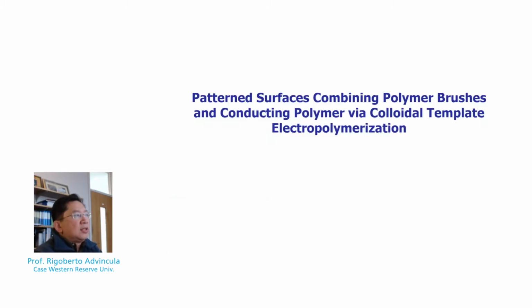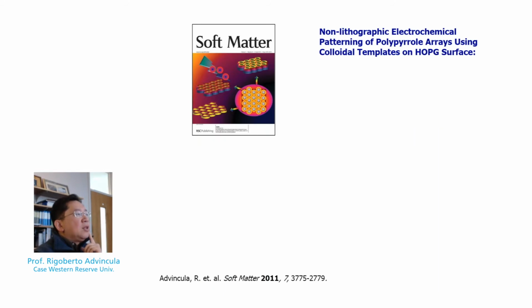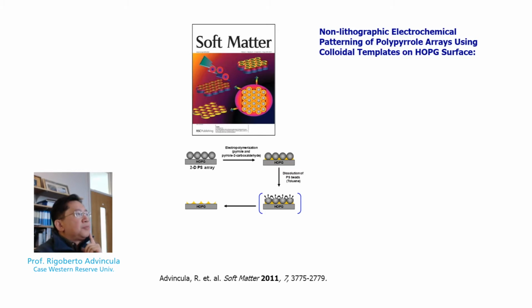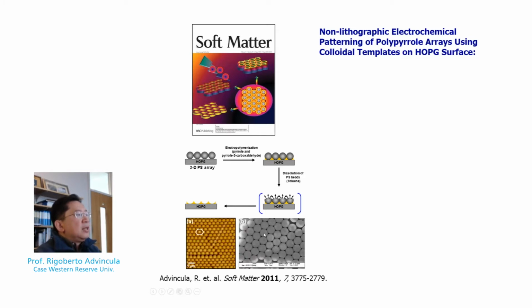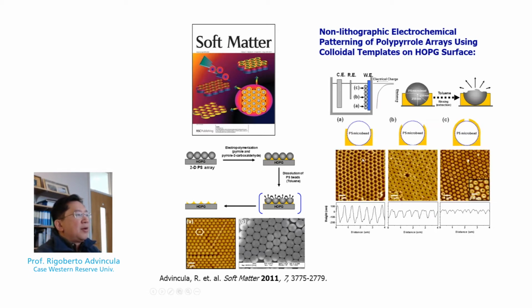So I'd like to do this last example by showing how we have patterned polymer brushes using colloidal templates. Back in 2011, we demonstrated that colloidal particles can be used to pattern surfaces, where the colloidal particles can form a hexagonally packed structure as shown here. The interstitial spaces provide a way for electrodeposition, let's say, of a conducting polymer on the electrode surface. Hence, by masking or using this as a template, one can observe the formation of arrays, as shown here. So these arrays are basically conducting polymers that were deposited at the interstitial spaces in between the particles, resulting in a honeycomb, half dome, or a full dome structure as shown here.